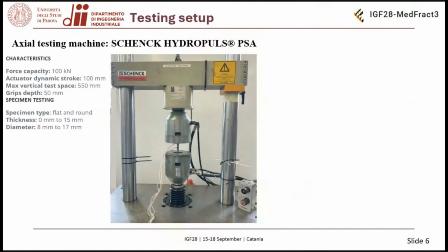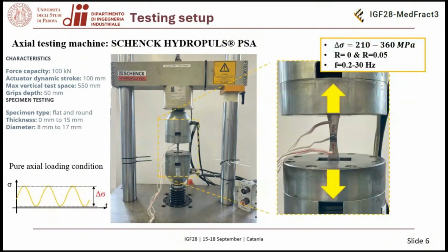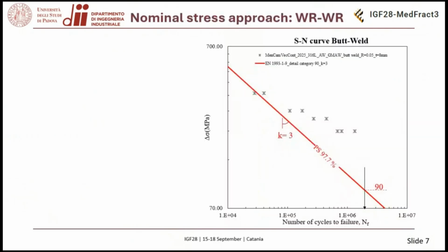We performed the test with a servo-hydraulic machine by applying a pure axial loading condition with the loading ratio almost equal to 0. And here you can see the result. This is the first series, the traditionally manufactured welded joints. And here the red line is the design curve provided by the Eurocode 3.